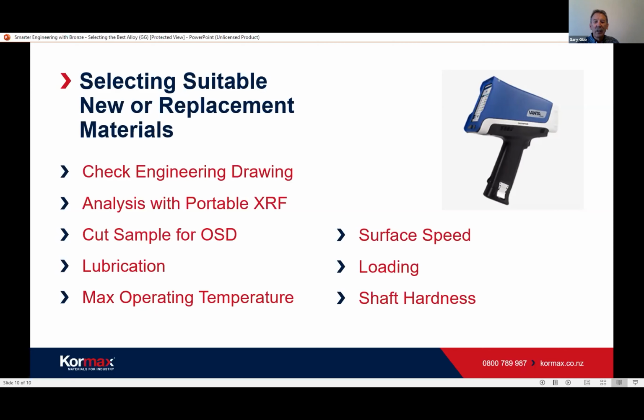The other thing you've got to look at is the surface speed, certainly for a bush or wear surface. The higher the surface speed, the better lubrication you need. Some alloys at high speeds, if you don't have enough lubrication, the aluminium bronzes suffer from a thing called galling, where the metal transfers from the bush to the shaft, and that causes shaft failure, bearing failure.